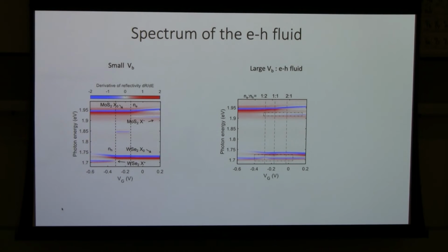So here I just show you the optical spectrum when we inject the electrons and holes in the system. On the left-hand side, we apply a relatively small bias voltage. In that case, we can have only electron doping in this region and hole doping in this region. So what you can see is when it is electron doped, we can see the exciton and the trion feature for the MoS2 layer. And when it is hole doped, we can see exciton and trion signal for the WSe2 layer. So on the right-hand side, I show the behavior when you apply large bias voltage.